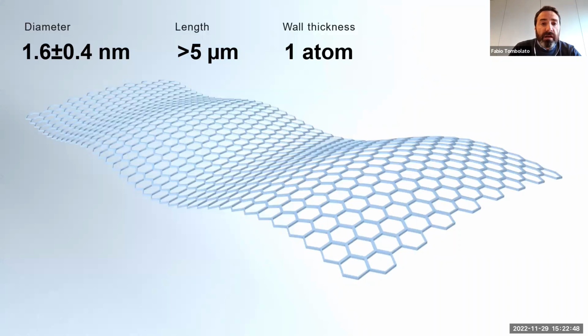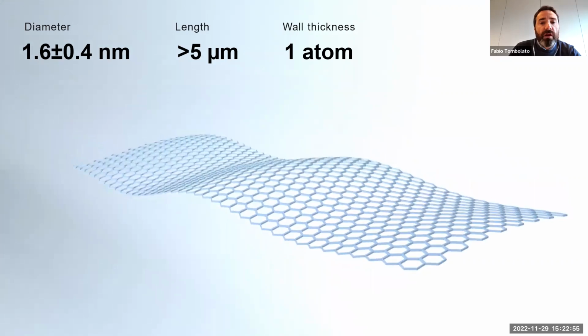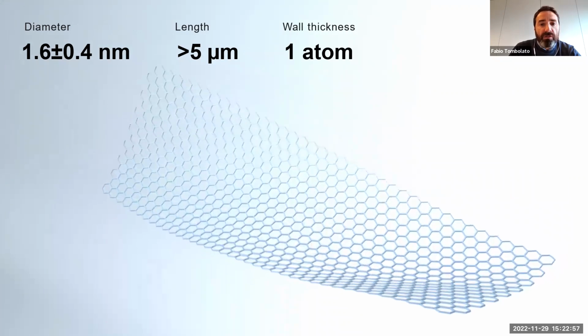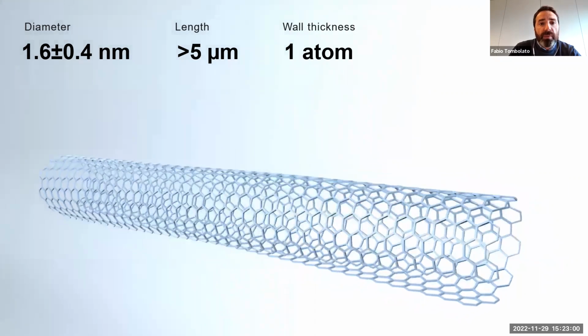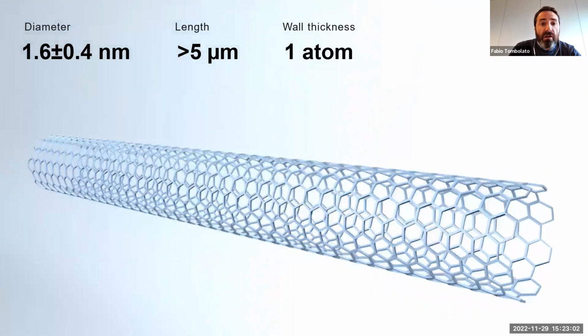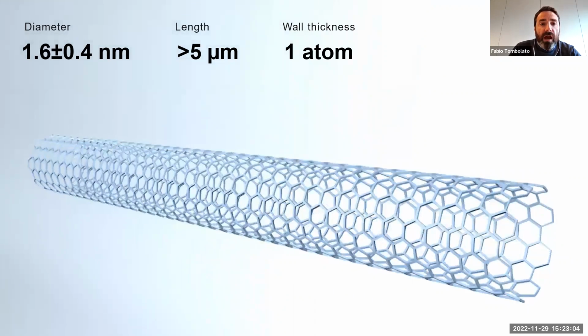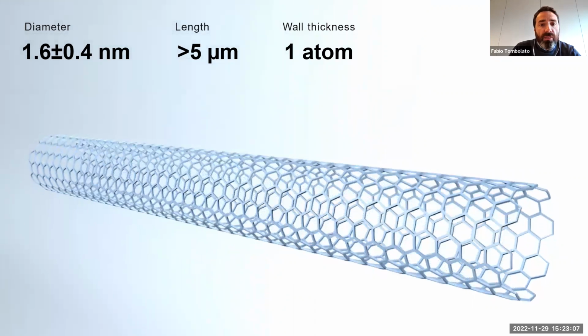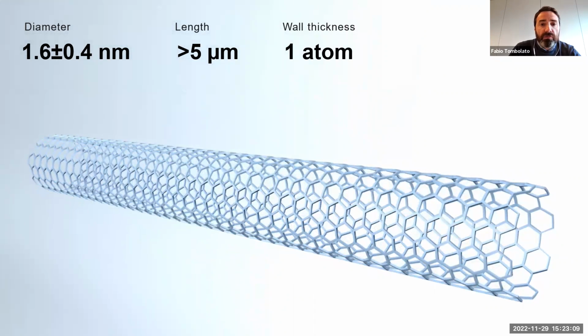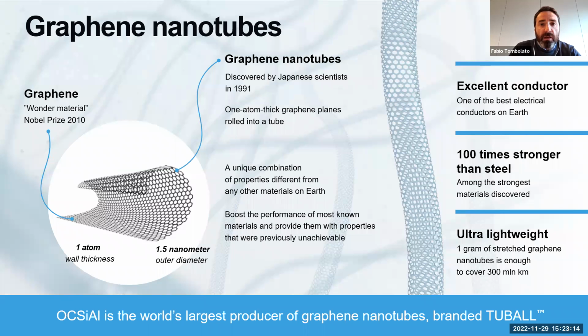Graphene nanotubes, they are also called single-wall carbon nanotubes, are namely made by a single sheet of graphene that is rolled up to form a very long, more than 5 microns, and very thin, less than 2 nanometer, flexible tube. Flexibility, together with a very high aspect ratio, together with a wall thickness of only 1 atom, give to this material peculiar properties. Graphene nanotubes were discovered in the early 90s, and they are known as material with unique properties compared to all the other materials that are on the Earth.